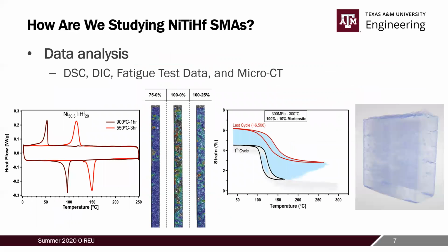So what methods are we using to study these nickel titanium hafnium shape memory alloys? The primary methods we're using include differential scanning calorimetry, digital image correlation to look at localized strain during fatigue tests, other fatigue test data, and micro CT imaging.